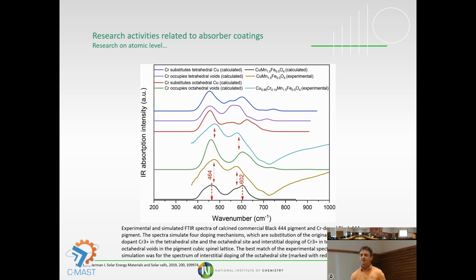We do some modeling as well. In order to confirm where the dopants really are, we simulated the spectra to confirm if those dopants are on the tetrahedral or octahedral sites, and combined those results with experimental infrared measurements. As you could see, we get a good match in order to model those dopants on specific sites, and we claim that is the reason why we get better absorption spectra at the end.